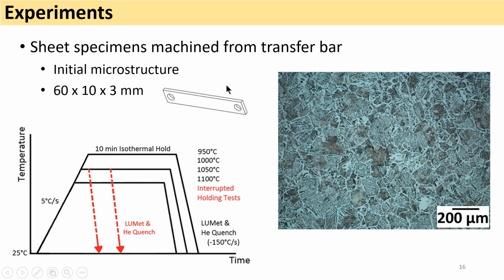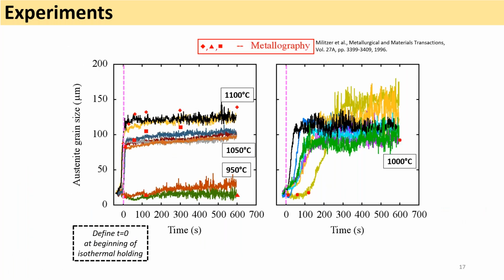This is the initial microstructure, and this is a typical sample used for the LUMet testing. Okay, so these are the results that we can see here. In the vertical axis is the austenite grain size, varying from 0 to about 150 microns, depending on the condition. And depending on the temperature, of course, you will have different limiting grain size. At 950, we can see almost no grain growth. Around 1050 degrees, we have a limiting grain size of about 100 microns, and at 1100 degrees, the grains are slightly larger, about 120 microns.